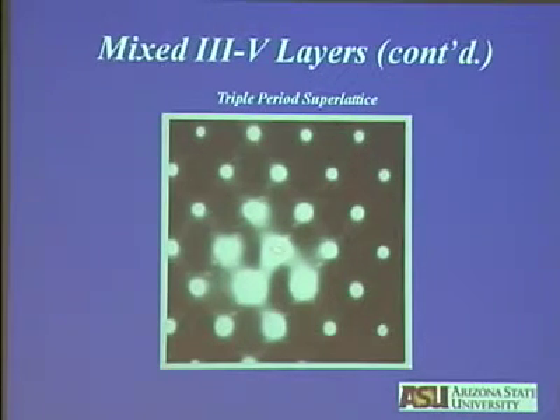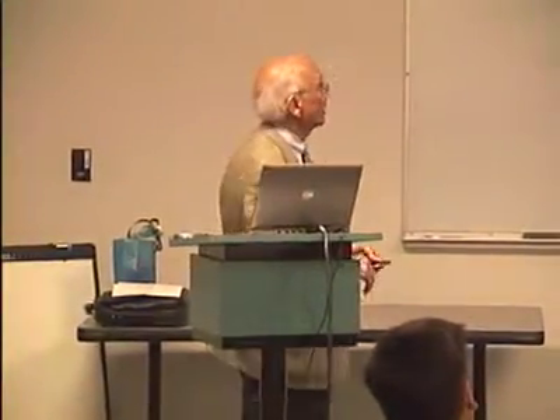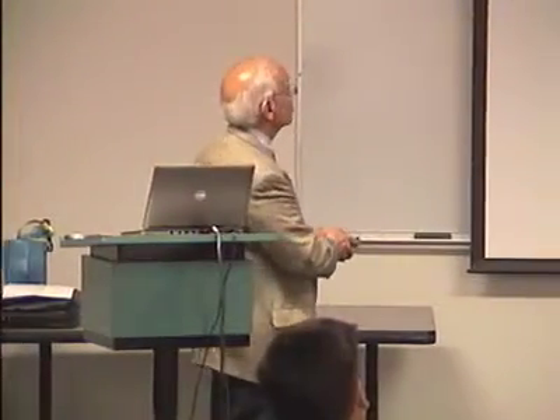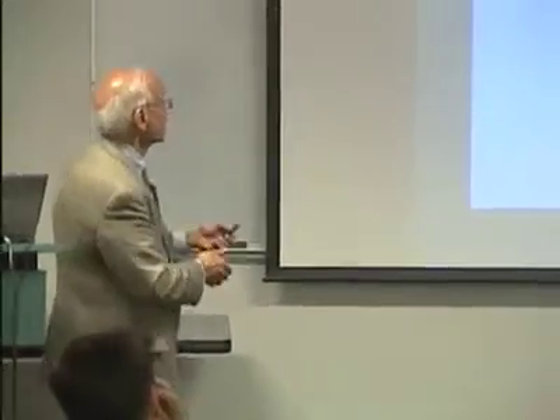And what you find is now you have a triple period superlattice. This is the Bragg spot, superlattice spot, superlattice spot, back to Bragg spot. So the period now is a triple period instead of the double in the earlier case, and that's what is shown here. The streaking of the superlattice spot is due to the imperfection in your ordered structure. They are very thin platelets. It's not a very good ordered structure, and that's what it is due to.